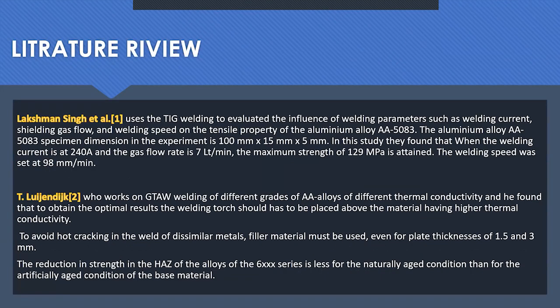I will discuss only one study due to time constraints. One of the researchers from New Zealand worked on the welding of two dissimilar aluminum alloys using GTAW. In his research, they found that to get the optimum result, the welding torch should be placed over the metal which has the higher thermal conductivity. And to avoid the hot cracking of the dissimilar metals, filler materials must be used, even if the thickness of the plate is less than 3 mm.